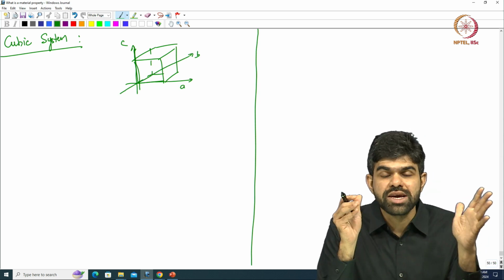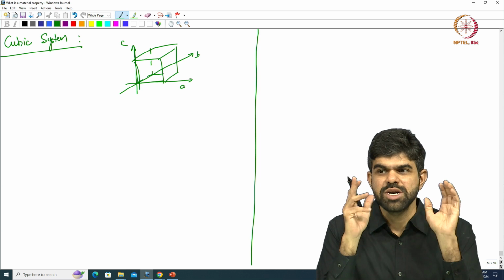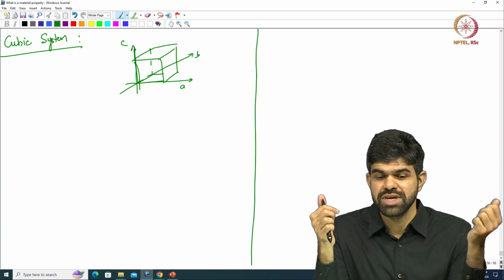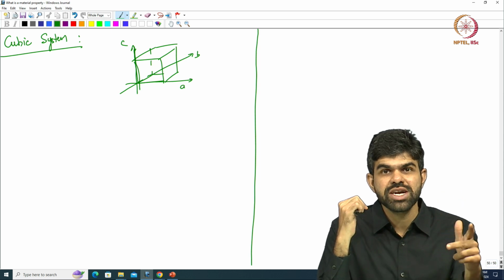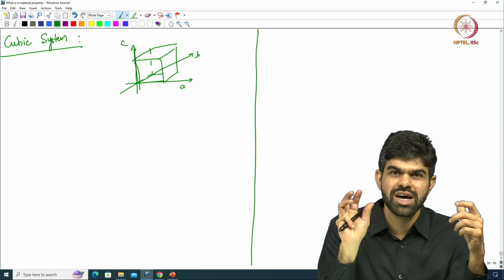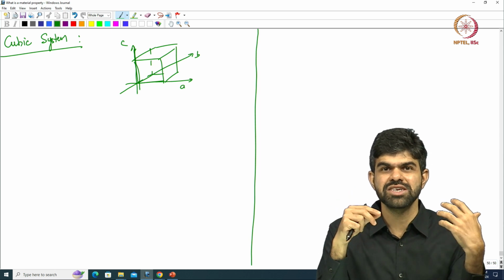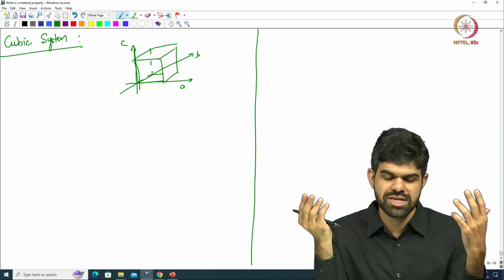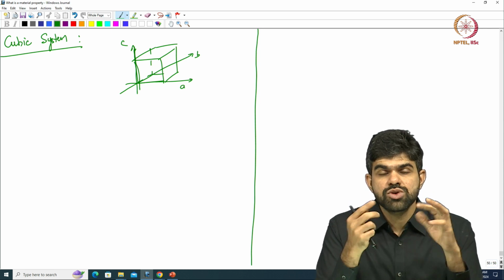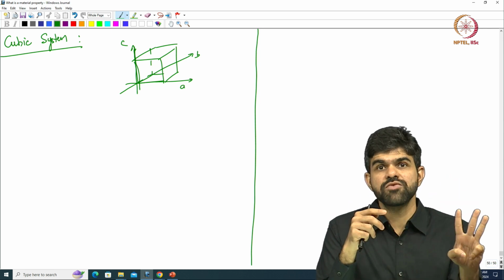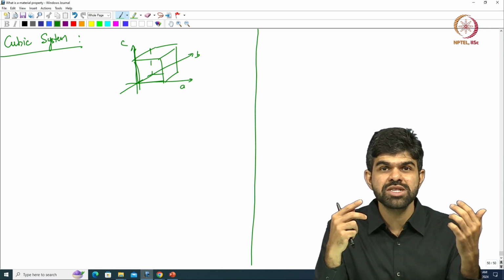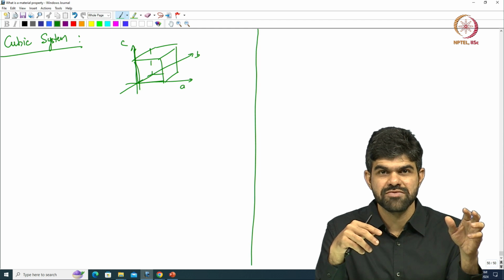So it looks like that if I am just looking at the unit cell, but I cannot say the symmetry just by looking at the unit cell, I should also look at the motif. But if I just look at A, B and C, it is a cube. So I should rotate this by 90 degrees in any direction and get exactly the same cube, but that is not necessarily true. What is true is that if I have three fourfold axes of symmetry, that will be a cubic system. What is not true is that for any cubic system you need three fourfold axes of symmetry.